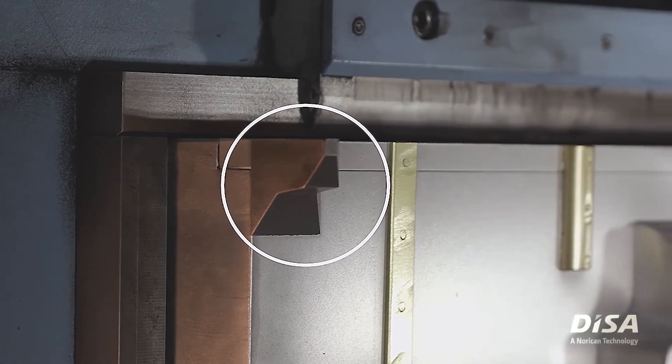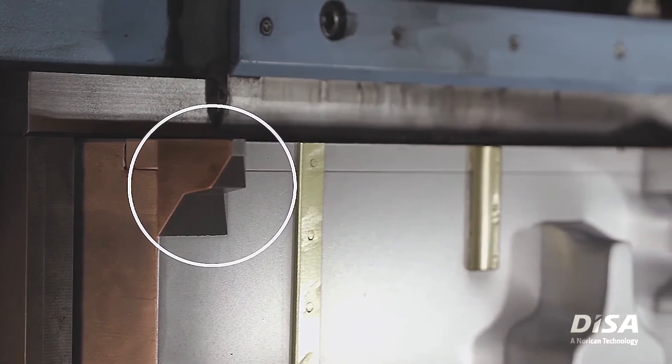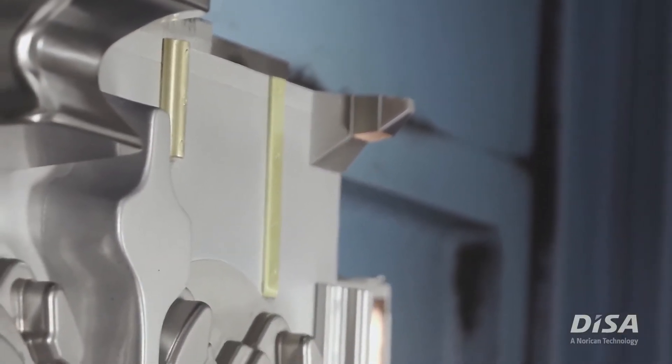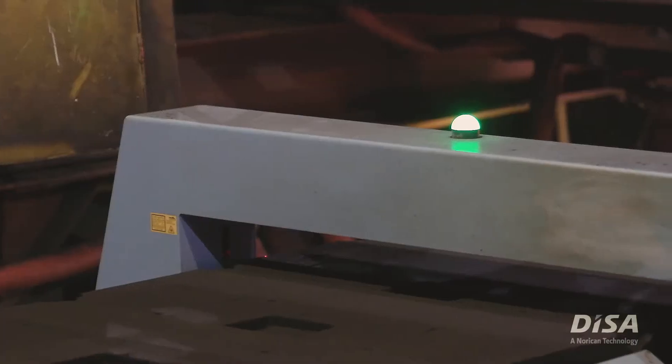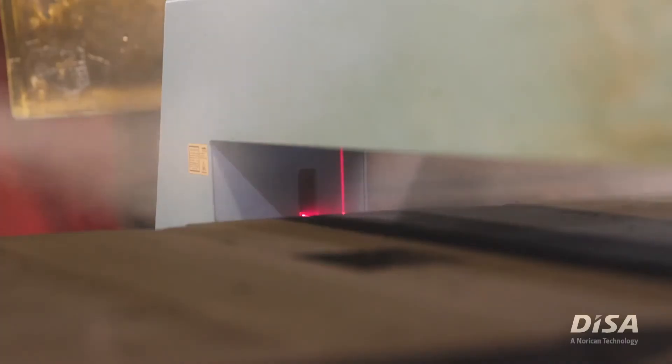To create markers for measuring on the outside of the mold, all four corners of both pattern plates are equipped with special MAC blocks. These blocks are precisely positioned in relation to the casting cavities. The MAC blocks add mold impressions that are directly linked to the hidden casting cavities visible from the outside when the molds are closed. The sensors scan the outer visible surfaces and impressions in each corner of the mold as the mold string passes through the laser grid.